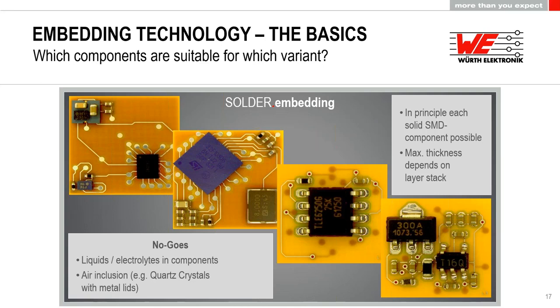And there are some other no-goes, I would call them. If you have any kind of liquids or liquid electrolytes in your component, this will give you issues. Maybe we could build the PCB, but if you go, for example, to an additional temperature step like soldering, you might run into the risk of the classical popcorn effect. The liquid inside the component starts to boil, you get a vapor and a vapor pressure, and basically your PCB explodes like a popcorn.